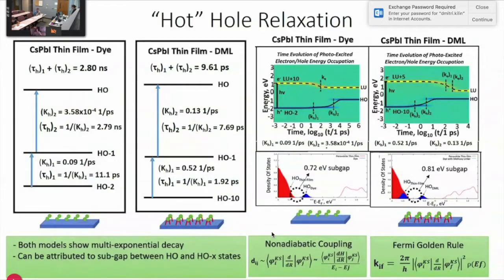I guess I forgot to mention that using the non-adiabatic couplings, our transition rates can be computed using the Fermi golden rule. So we put the non-adiabatic couplings into the Fermi golden rule, as shown on the bottom right, and then we can use that to represent non-adiabatic transitions in these systems.